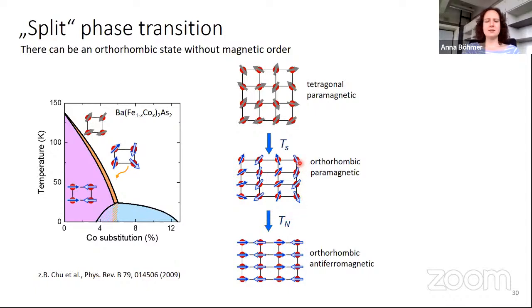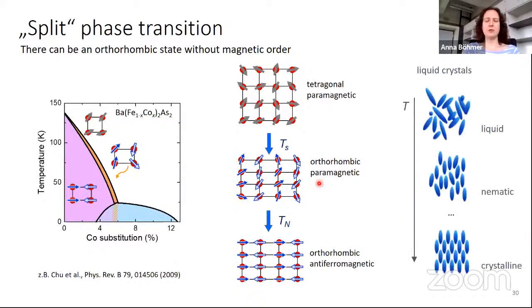There can be a state that's no longer square, but the magnetic moments are still disordered. If you think about it, it's strange, because we said this is no longer square because of the magnetic order. And now it turns out you can see this being no longer square in a disordered state. What does it mean? We worked on it and we found out, but we need a name for that state.